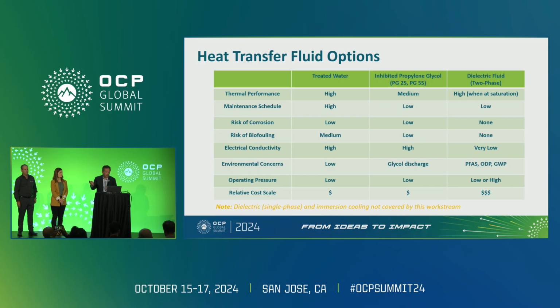For electric conductivity, the best performance is dielectric fluid. For environmental concerns, there's PFAS for the dielectric fluid, and glycol in the discharge for PG25. Some municipalities have issues with discharging it. For treated water, there's no issue at all. The cost is relatively low for treated water and PG25, and for dielectric it is a little bit higher.